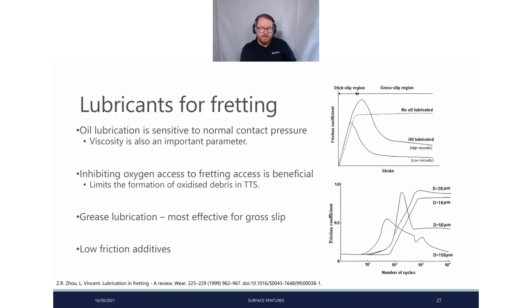Oil lubrication is very sensitive to normal contact pressure, and viscosity is extremely important because you don't want your lubricant to just be squeezed out of your fretting contact if your pressure is too high. However, if you can optimize this properly, you can get a quite good reduction in your friction coefficient, as we see in the diagram at the top. So you will get an increase in your friction at first. All of these have to stabilize first, and then the friction will drop.